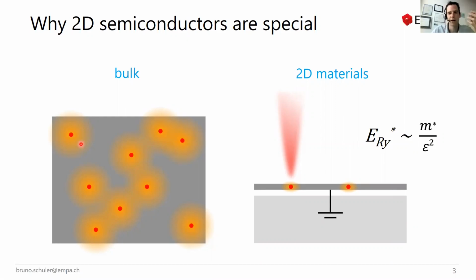And normal shallow dopants have a binding energy of only a few milli-electron volts, so they can be excited thermally and so on. Now in 2D materials, the picture is a bit different. The reason is that in 2D materials, the effective mass is larger in general, and the dielectric screening is much smaller. So this leads to the electronic wave functions being much more confined.